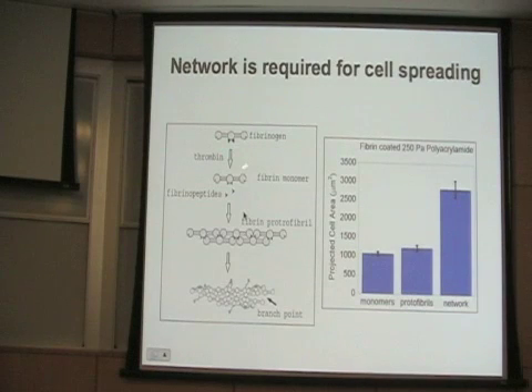So we've looked at taking polyacrylamide gels and giving them as the cell attachment site the polymers that make the fibrin network, right? But not a polymeric network of fibrin with its own intrinsic nonlinearity, but just the building blocks of the fibrin network. Either the enzyme-activated monomers, or the thin protofibrils that will eventually make the network, or the big fat fibers. As long as you trap the reaction before the gel point, you can make soluble filaments and covalently link them to the top surface of the polyacrylamide gel.